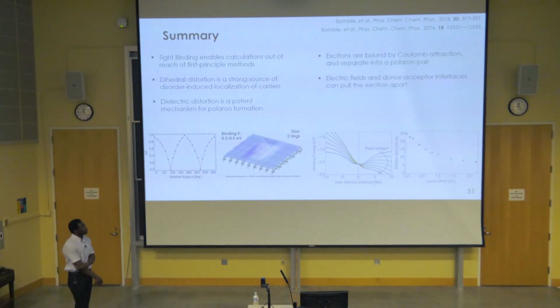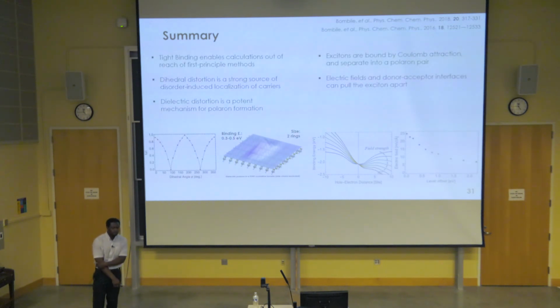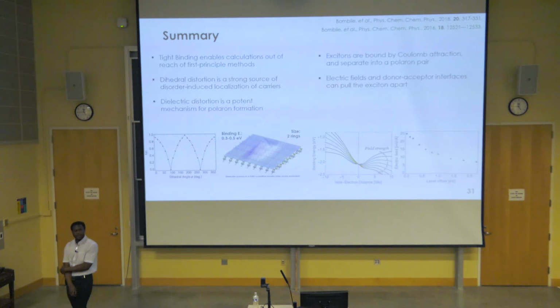We've also looked at excitons as an electron and hole pair bound by Coulomb interaction, dissociating and separating into two polarons. And I've also shown you the effect of the electric field and a donor-acceptor interface on the exciton, which pull the charge carriers apart, making it easier to unbind them.